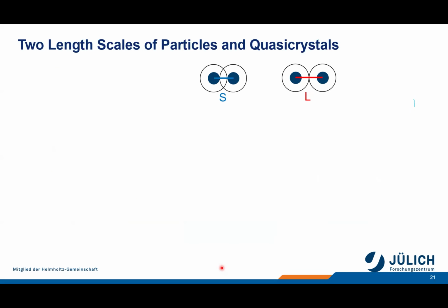So the question then is, if you have these two intrinsic length scales, how does this translate into a structure or distances between particles or atoms? So if we have our core shell system, if the shells interdigitate or squeeze together so that a shell edge would be in contact with the edge of a core, then we would have a small distance between the centers.